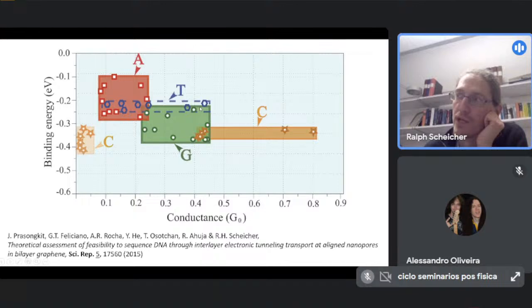And then guanine falls into this region here. Very little overlap with adenine, actually, so that's good news in terms of distinguishing between the 2 bases. And cytosine, quite interesting, we have a very broad range of conductances here, but they sort of fall into 2 groups, very large conductances and sort of average conductances. And also a group here which is very low conductance, where basically cytosine, being one of the smaller nucleobases, doesn't couple well to the graphene nanopore edges at all.